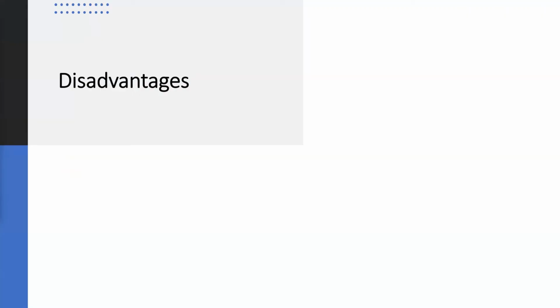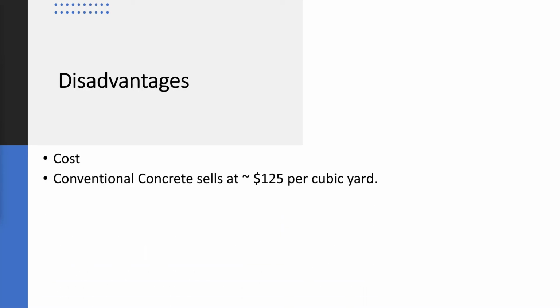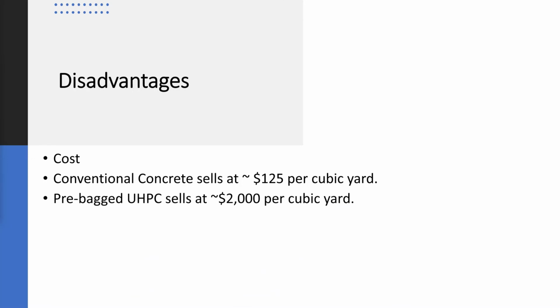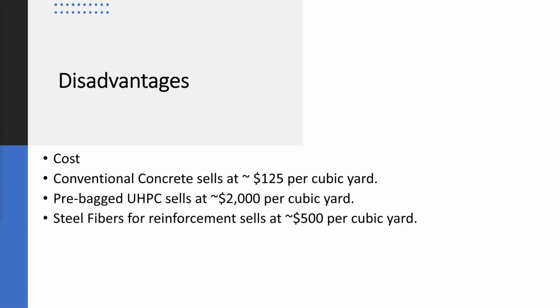So we've talked about all the advantages of UHPC. Now let's talk about the main disadvantage of it, and that being cost, of course. Conventional concrete sells at about $125 per cubic yard, while pre-bagged UHPC is at about $2,000 per cubic yard, and that's not including the steel fibers. The steel fibers for reinforcement sell at about $500 per cubic yard. Altogether, adding the steel fibers and the pre-bagged UHPC, we come to a total of about $2,500 per cubic yard, which is much more expensive than conventional concrete.